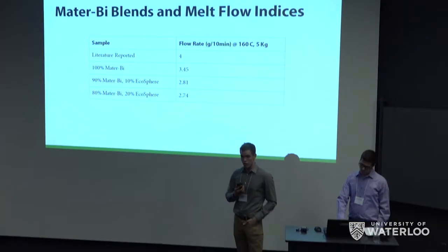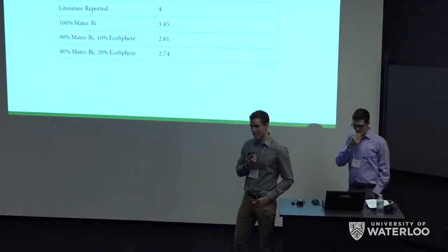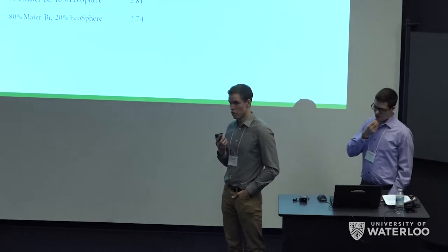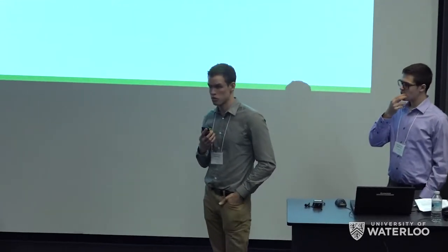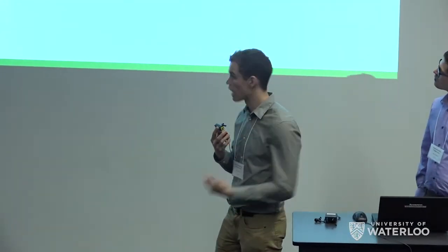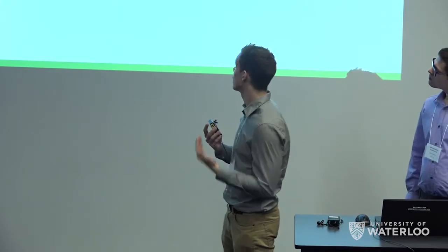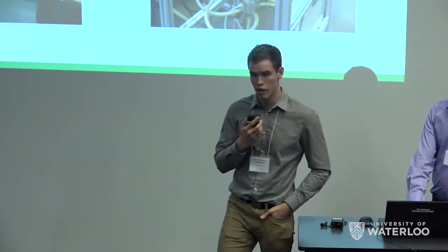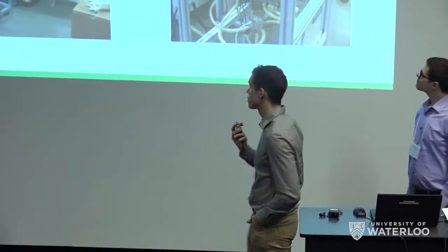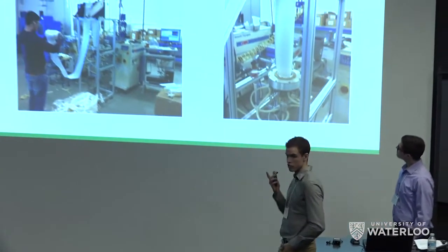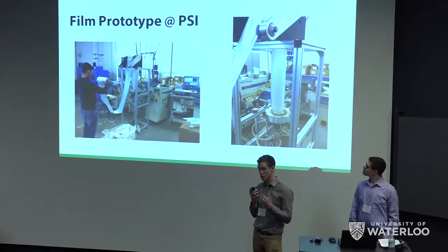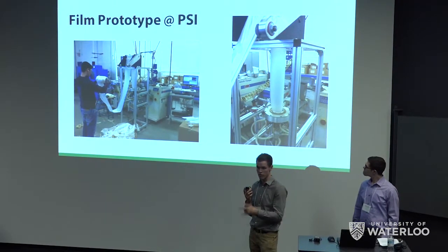Before we could go and manufacture this in the film blowing line, we needed baseline data on the melt flow properties of our material. So to do this, we just ran a simple melt flow test, and as we expected, the more EcoSphere we add, the slower it flows, which means it's a thicker material. So this helped us set the parameters when we were blowing this into a film. The next step is we went to a manufacturing facility, and these are pictures of us blowing our film and the virgin film, the virgin Mater-Bi resin, that you have samples of both of these.